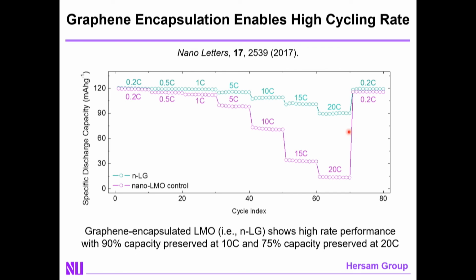Additionally, I'll point out that graphene is a highly conductive material. That means that a graphene encapsulation lowers the impedance of your battery, which allows you to increase the kinetics of the battery. In other words, you can go to higher cycling rate performance. That's shown here, where we're showing cycling at different cycling rates. 1C means we're cycling in an hour. 20C means we're cycling in 3 minutes. Pink is the control, where we see dramatic reduction in capacity at high cycling rate, whereas for the graphene-encapsulated case, you maintain much of your capacity even at 20C rate, which is, of course, of high interest for many applications, including electric vehicles.